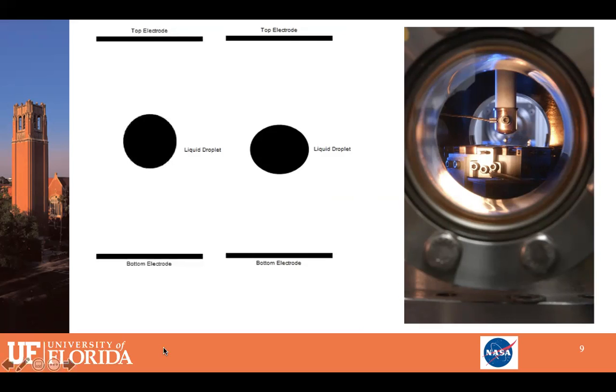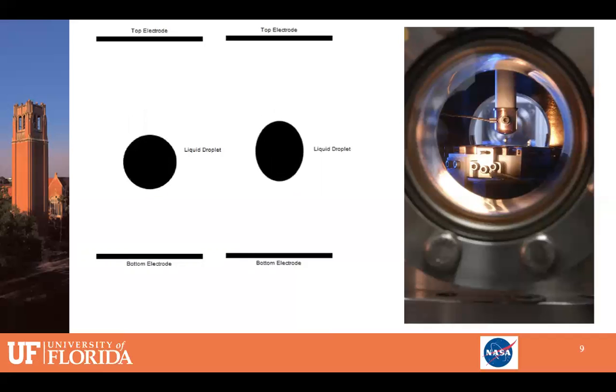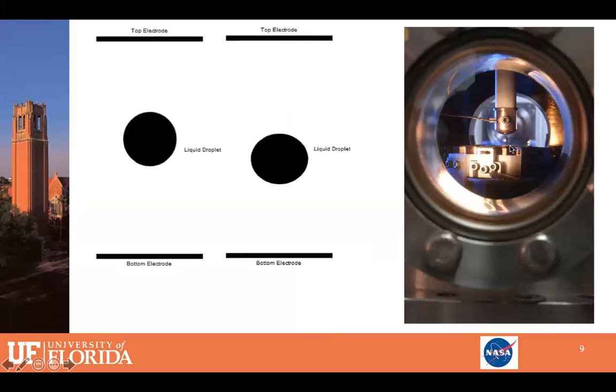This spherical drop will move like a solid, like a rigid body, up and down if the electrodes are subject to an alternating field. Now, if you keep increasing the frequency of this alternating field, then this rigid body motion of the sphere will change, the sphere will undulate, and you will get a certain mode. This mode will cause the drop, which was once a sphere, to undulate from prolate to oblate structures. Now, on the right, you've got a depiction of a solid suspended or effectively levitated between two electrodes. It will be heated by means of a laser and subject to this alternating field.